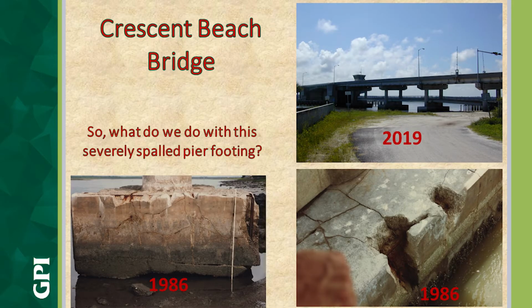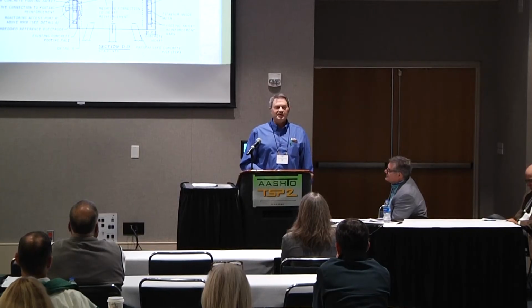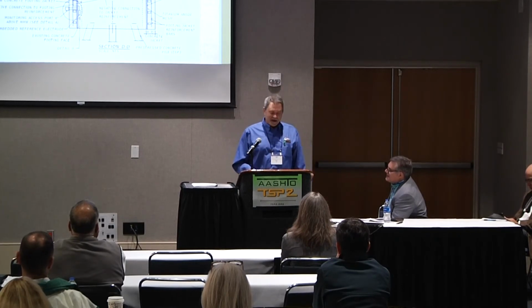So first, let's look at the Crescent Beach Bridge. It opened to traffic in 1975. You can see that by 1986, the use of low-density concrete, not enough cover, and poor construction all resulted in significant substructure spalling and degradation after only 11 years of service. I say we. I spent quite a bit of time at FDOT. I slip every now and then.